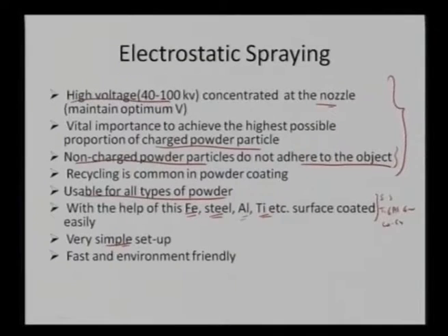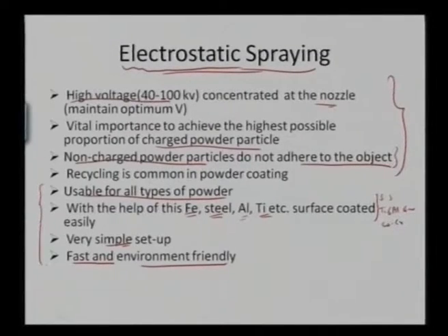It has a very simple setup, and it is very fast and environment friendly. In electrostatic spraying, we maintain a high voltage near the nozzle, and that voltage is utilized for creating a charge on a powder particle. Then we let this powder particle flow through and get deposited on a substrate, and then we can do some sort of secondary treatment, which can be fusing, basically the melting of those powder particles to get cured on the substrate. The extra powder, the overspray, can be recycled in a later stage. The advantage of this process is that we can easily coat a metallic implant using any type of powder particle which can get charged. It is a very simple setup, very rapid, and at the same time environmentally friendly because it is not generating any fumes.